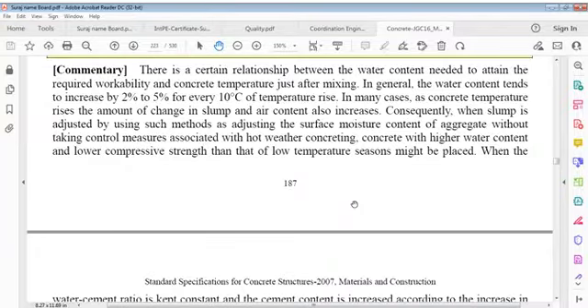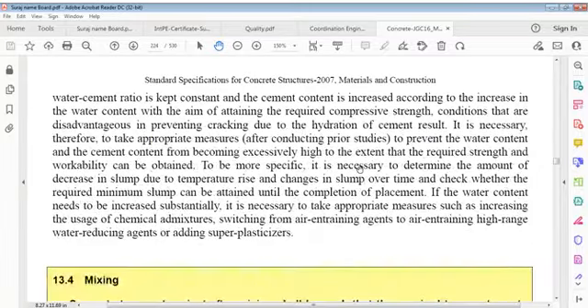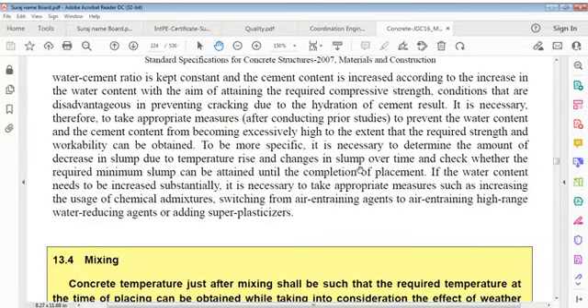Consequently, when slump is adjusted by using such methods as adjusting surface moisture content of aggregate without taking control measures associated with hot weather concreting, concrete with higher water content and lower compressive strength than that of low temperature seasons might be placed. When the water-cement ratio is kept constant and cement content is increased according to the increase in water content with the aim of attaining required compressive strength, conditions that are disadvantageous in preventing cracking due to hydration of cement result. It is necessary, therefore, to take appropriate measures to prevent water content and cement content from becoming excessively high, to the extent that required strength and workability can be obtained.